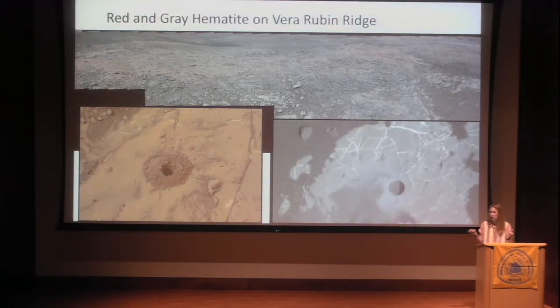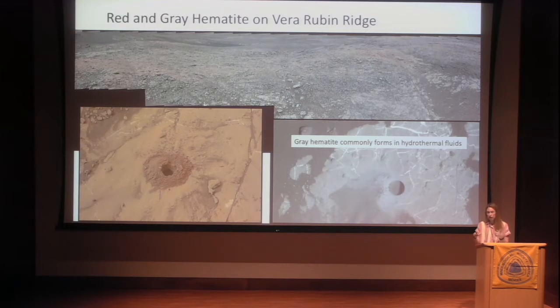We also drilled one of those gray outcrops, and this is the Highfield drill hole. This sample also had abundant hematite. Again, that was a surprise to the team because of the gray color, but of course this just means there's gray hematite present, and gray hematite is more coarsely crystalline than red hematite, where crystallites with a size above 5 microns, I think, appear gray. But what's important also about gray hematite is that it commonly forms from the recrystallization of nanophase iron oxides like ferrihydrite in hydrothermal fluids. So this could be a hydrothermal indicator here.